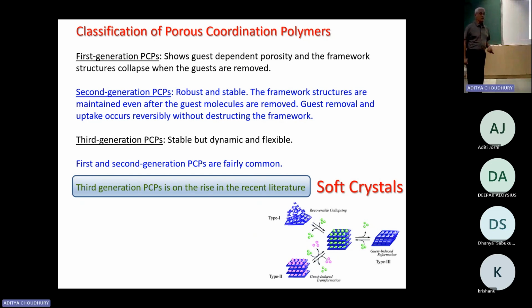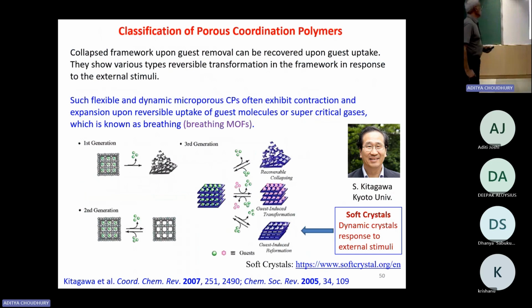It is stable, but dynamic and flexible. This is more interesting. Many people started working on this third generation. Here, the structure might change when you remove the solvent, and something else, a guest, may also occupy it, and that may change the structure. It's called type 3 structure, third generation, which is rising in the literature. That means more and more third generation MOFs have been discovered. They call them soft crystals. Okay. So we talk about soft crystals, the collapsed framework. Okay. So this is first generation, second generation, third generation, and the third generation can further be classified